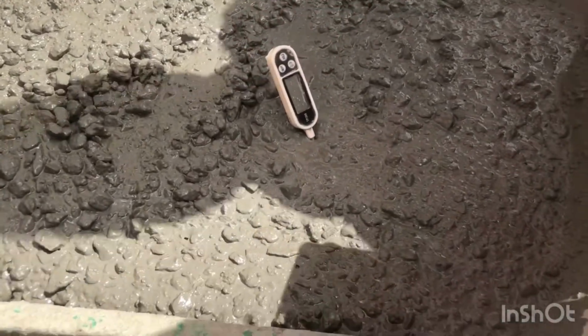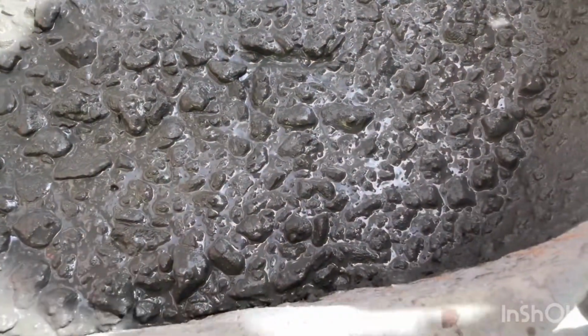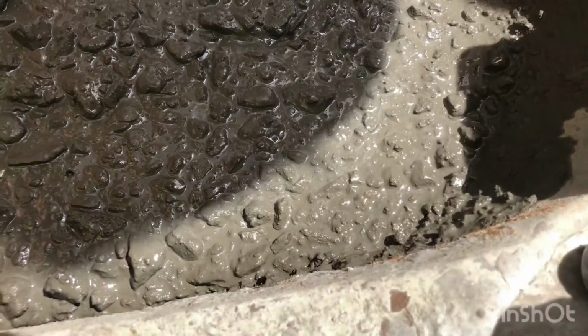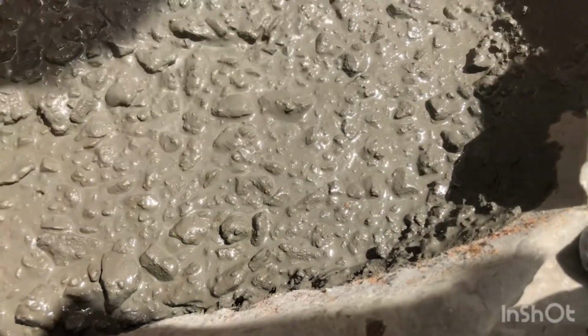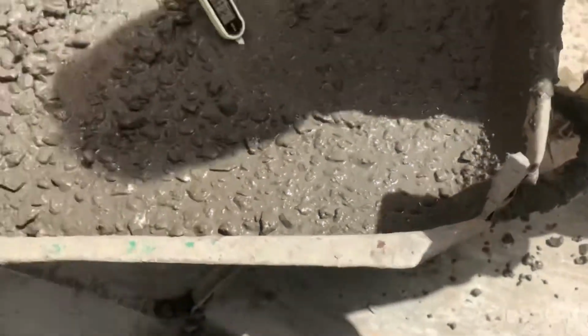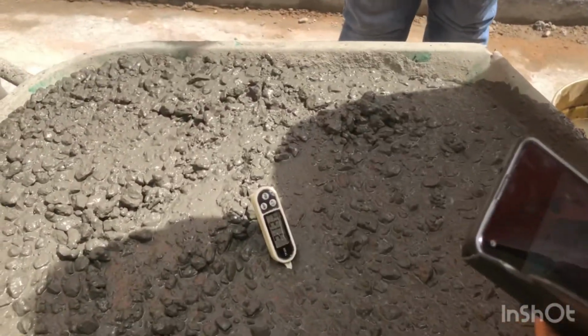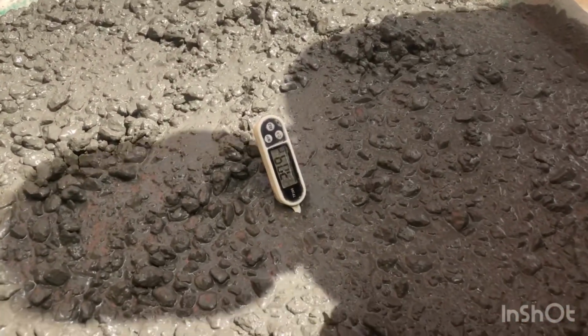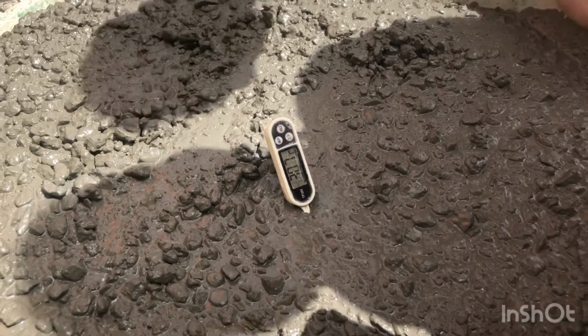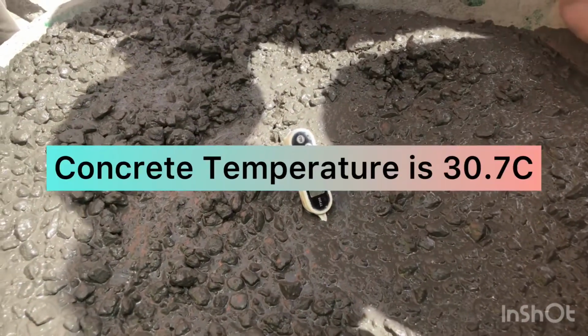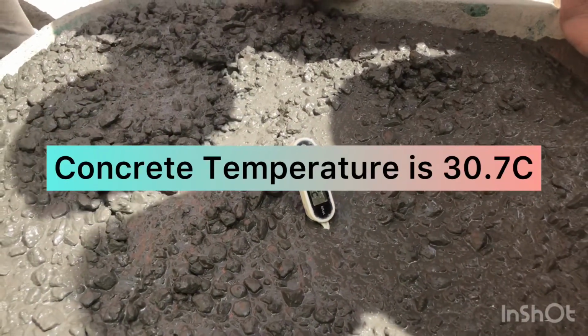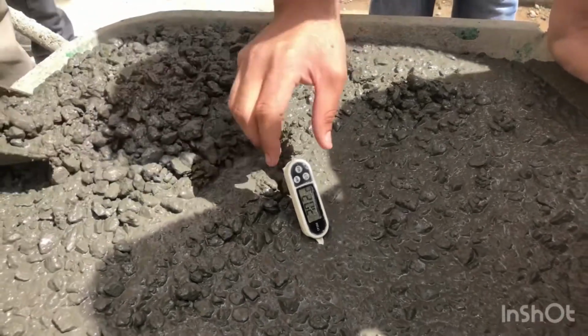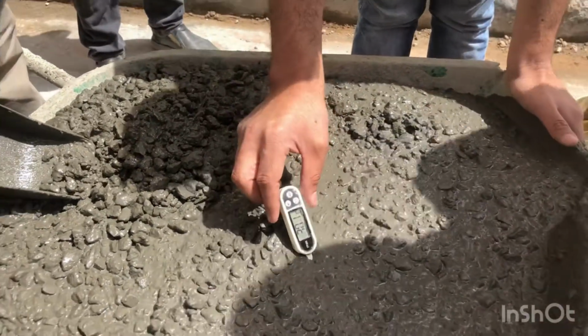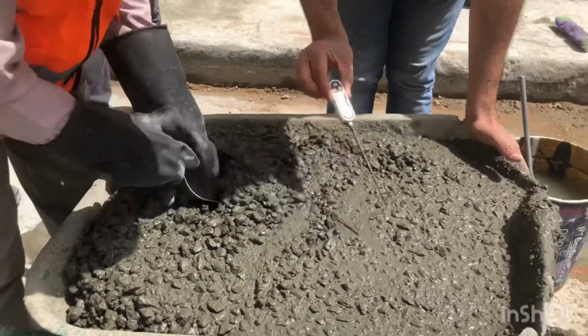First of all, when the concrete mix is ready, first you have to check the concrete temperature. Normally concrete temperature should be from 20 to 36 degrees centigrade, but here we will see what the temperature of concrete is. Let's see. Here the concrete temperature is 30.7 degrees centigrade, meaning its value is according to specs and codes.